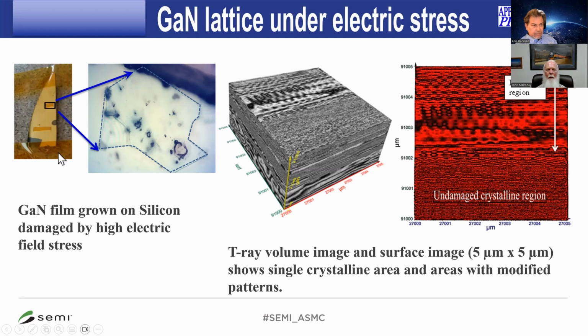These GaN films are deposited on this silicon wafer, which was then subjected to high electric field stress. That experiment was not done by us. We got the sample as is after they performed the high electric field experiment. And the point was, when they looked at this spot under a light microscope, they saw these dark spots here and there.